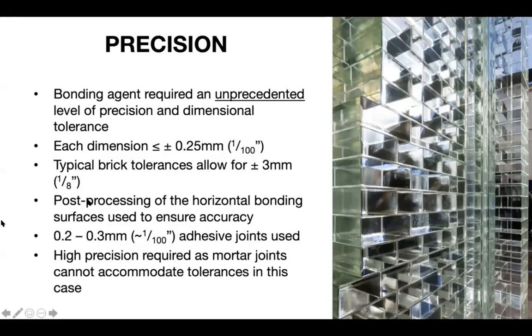In some cases, post-processing of that horizontal bonding surface was used to ensure accuracy. So essentially polishing and grinding down those top and bottom surfaces to make sure the bricks are perfectly level, and they're also within these very, very strict size tolerances for the project. To bond the bricks together, an adhesive joint of 0.2 to 0.3 mm was used, or again, roughly 1/100th of an inch for that adhesive as well. The high precision was required as mortar joints cannot accommodate tolerances in this case.